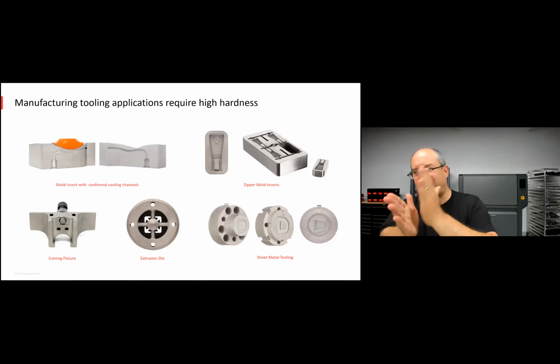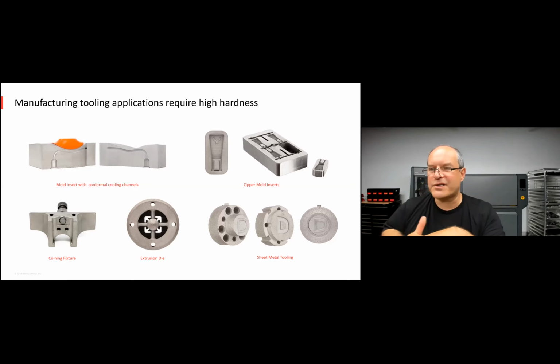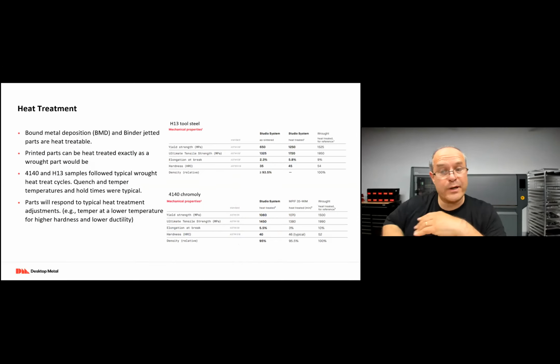You literally can take a slice and you cannot tell from the crystal structure or from the grain size what the image looks like. You cannot tell the printing orientation. But one of the consequences of them coming out fully annealed is they're relatively soft. So relatively soft could be 27, 30, 32 Rockwell C hardness. Now, for many applications, that's perfectly fine. But if you want even higher hardness, whether it's tooling applications or other reasons you might need something to be very hard, you may want to harden the parts.